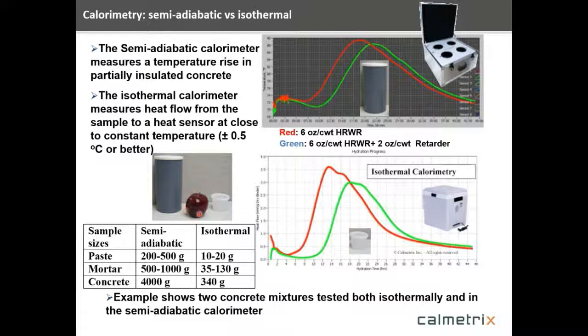Below here is a photograph that graphically illustrates the difference in sample containers. This is the 125 milliliter sample cup that we use with the isothermal devices. These are reusable sample containers. You can see here that the sides are angled, so it's very easy to pop out the cured sample once the experiment's done. And then here are the larger sample containers that we use for the semi-adiabatic. These are either 3x6 or 4x8 cylinders. Down below is the typical sample size that we use with the instrument. Of course, with the isothermal and the smaller sample cups, we have smaller sample sizes compared to the semi-adiabatic. But in all cases, both with isothermal and semi-adiabatic, we can run paste, we can run mortar, and we can run concrete. And that's very important when you start looking at especially competitive instruments.